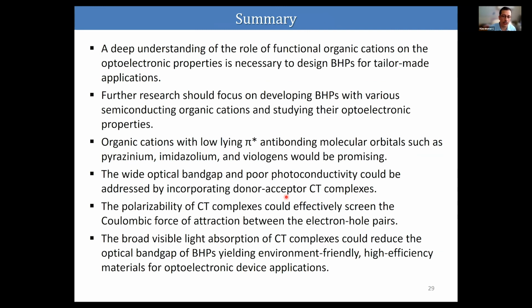And further research should be focused on developing bismuth halide with various semiconducting organic cations. We already proved that they are very good for improving the optoelectronic properties, and we can look at molecules like pyrazinium, imidazolium, or viologens. They may be good candidates. And in addition to that, we can incorporate charge transfer complexes into the perovskite structure, and they would yield very good visible light absorption.